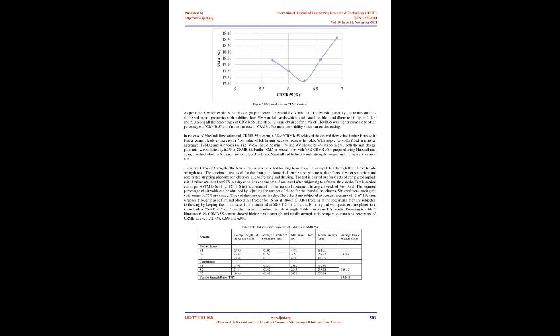After that, samples are kept in a water bath maintained at 60 degrees Celsius for half an hour. Then the specimens are tested in the Marshall testing machine and stability and flow are noted. Then the specimen properties are calculated and illustrated. 3. Results and discussions.